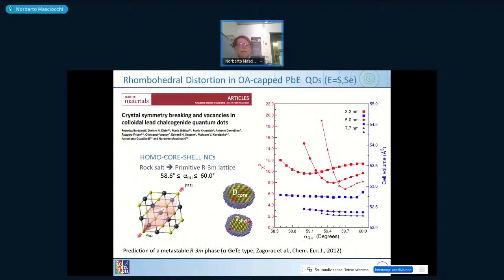The last point is the lead sulfide system. Lead sulfide is known to be cubic and has been cubic for 100 years. In 2012, it was proposed computationally that it should spontaneously distort into a rhombohedral phase by just elongating one of the diagonal axes. So the idea is, can we prove this by high resolution synchrotron data and our method, which is capable of catching small picometer changes in position.